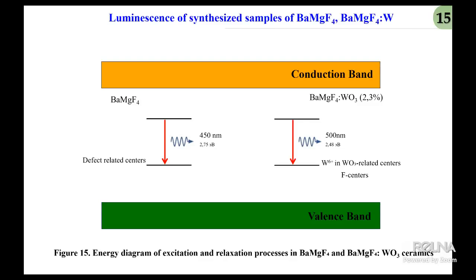Activation with tungsten ions changes the energy structure of the material, and new energy levels are formed. These are tungsten-related centers and fluoride vacancies, F centers. This leads to the appearance of an intense luminescence band in the 500 nanometer region. Thus, the introduction of tungsten oxides modifies the charge carrier relaxation mechanisms, creates more efficient radiative channels, and enhances the luminescence intensity of ceramics.